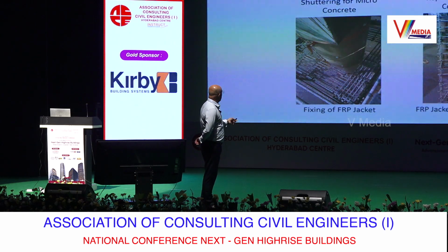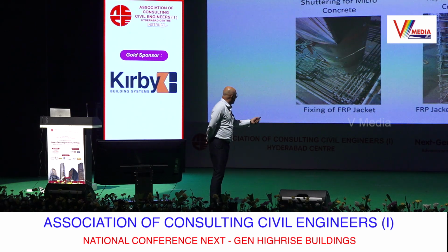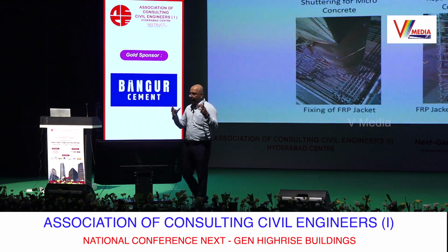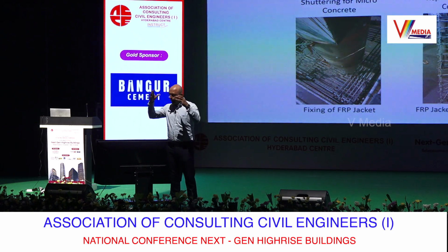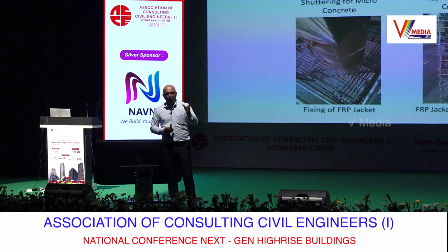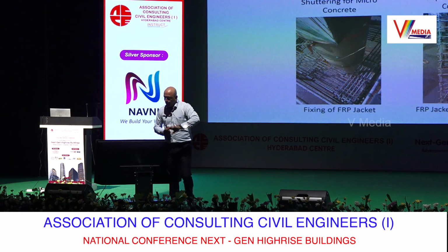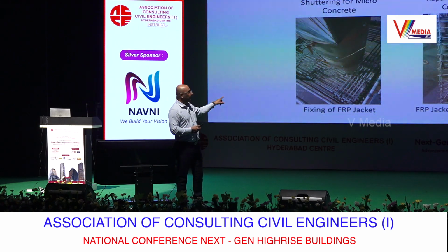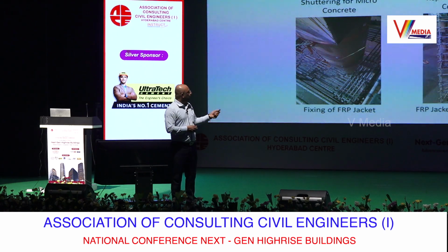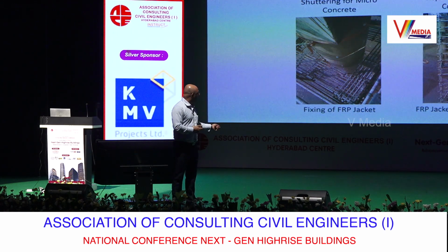So this is the technique we adopted. This is the encapsulation technique. So what you do is, there are fiber jackets, you take those jackets. After you remove the pile liner from inside, just fix this jacket, rivet the jackets, and through a high pressure pumping system, you pump epoxy. There are epoxy resins, underwater epoxy resins. You pump it like a paste. So you pump from bottom to top.